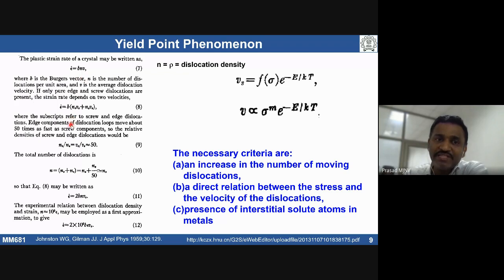So, if you take both edge and screw dislocations, we get this kind of equation. Usually edge dislocation loops move about 50 times as fast as screw components. That's why most explanations use edge dislocations, not screw dislocations, because edge dislocations can move faster than screw dislocations.